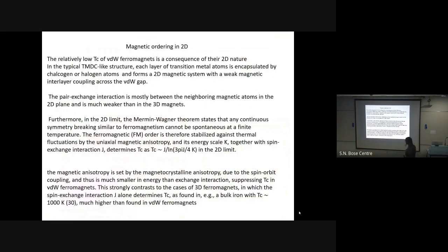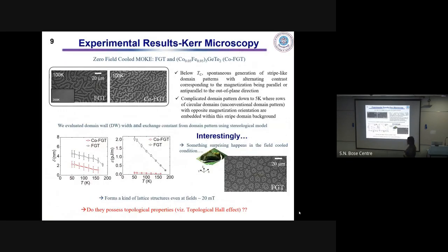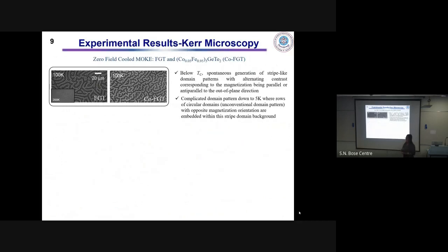Okay. So we have also done some collaborative work where we have exfoliated the FGT crystals and made flakes. There are also reports where they have shown that below a certain thickness, they do not observe the topological Hall effect. However, from our data, at a measured thickness of around 30 nanometers, we could still see a topological Hall effect, but that work is still in process right now.